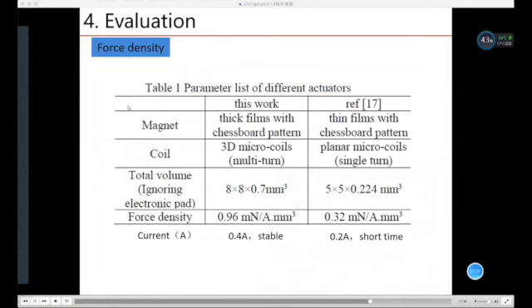Then this table compares the performance of this work with the previous work. In this work, we define the force density parameter, which is defined by the force divided by volume per unit ampere input. The force density of this work is 0.96 millinewton per ampere per millimeter square, which is 3 times our previous result. Furthermore, this actuator can take a stable input current of 0.4 ampere for long-time use, which is also a good advancement.